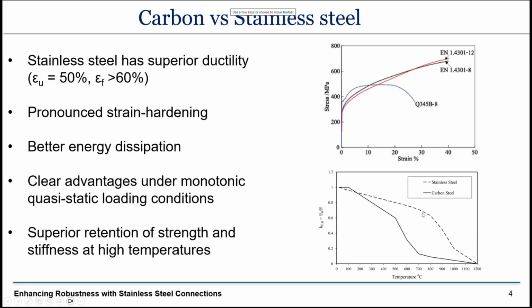So in case of a fire, the connections are expected to behave better. I would also like to draw your attention to that very limited part of the curve here, where we can see that for relatively low high temperatures, if I can say that, stainless steel loses a bit of strength and stiffness, a bit more than carbon steel. And you will see why this is important, because some of the findings we got are explained from that.